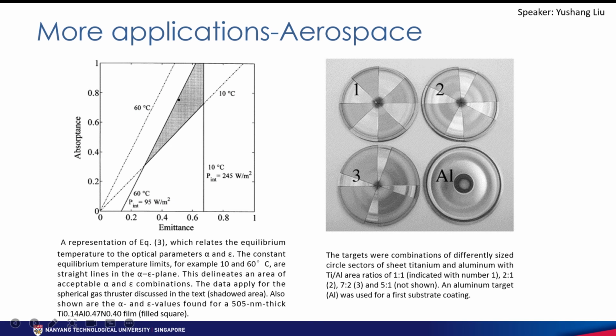Maria Brogren and colleagues found that titanium aluminum nitride coatings are a significant choice for satellite temperature control. The pictures show the representation and their samples, which turned out to be a great success, but are still not suitable for different temperature ranges. If the coating design ideas in this paper can be applied to aerospace thermal control coatings and make them temperature adaptive, it can extend the surface life of aerospace equipment and let it work stably.